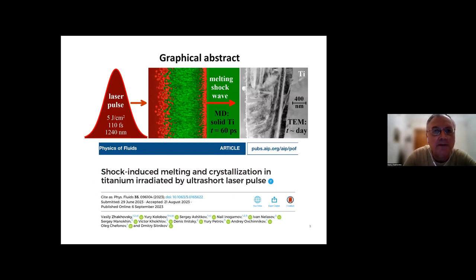And the graphical abstract on the top illustrates three main parts of our work. The experiment was performed with a laser pulse having energy about 5 joule per centimeter square, but emitted for a very short duration, 110 femtoseconds. This pulse hit the surface of the target, just pure titanium. Of course, in the middle you see simulation results, because we have no access to such early times, within just several nanoseconds, for the evolution of the material.